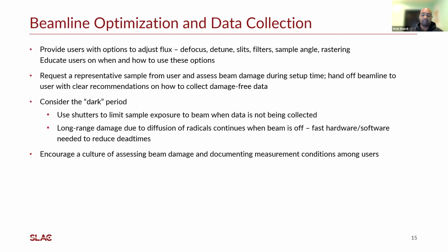I think this is highly sample dependent, and it's very highly dependent on how the sample was prepared. So I don't think we can consider a minimum flux where there's definitely not going to be any damage. And this is why it's so important to include details like the flux when reporting the data, so that if I'm working on a new sample and I don't know if the sample will experience beam damage, I can at least look in the literature for similar examples and see what conditions those were measured under to try and understand how my sample would behave.